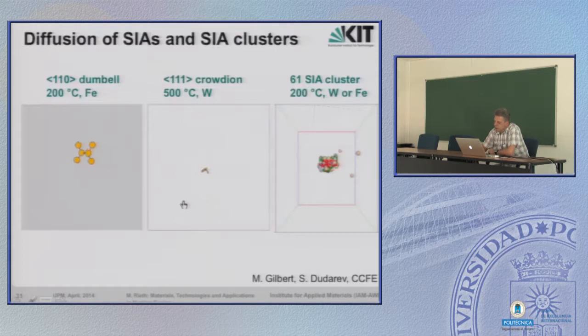This is the difference in terms of motion inside the lattice, because if you think that all these defects remain still for all times, you are wrong. They move, they can diffuse, they migrate through the lattice. This is the case for the dumbbell, and here in a few seconds the crowdion will reappear again. Here it is. And here is an example for a self-interstitial cluster. That's more than three atoms clustering together in interstitial places.